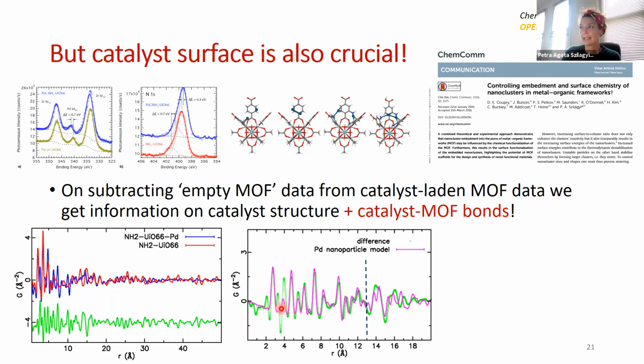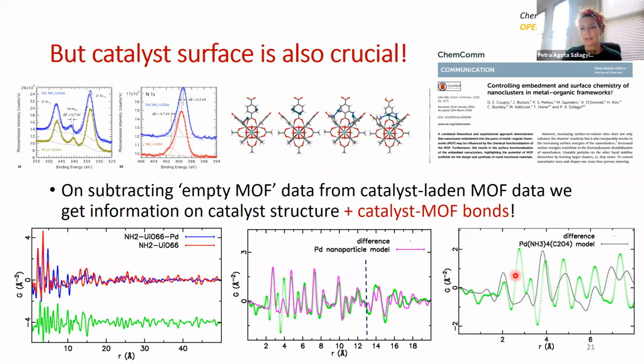And the palladium short range order is in very good accord with the palladium bulk crystal structure. However, we have some additional peaks here which we cannot account for. And in particular, this peak here could be assigned to a palladium nitrogen bond.